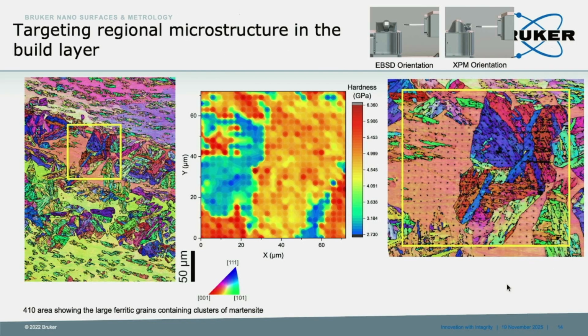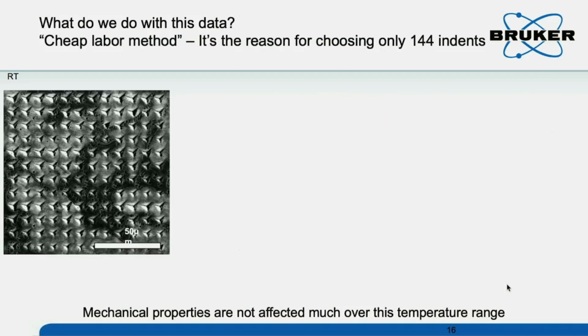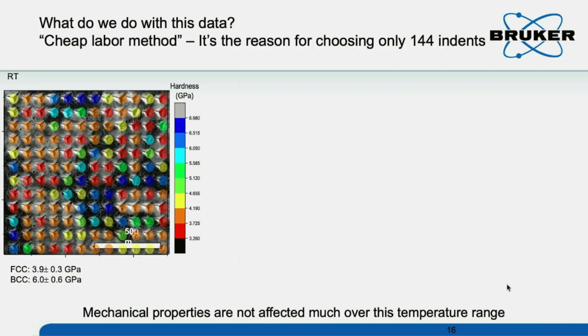And this is also an example of another material with high-speed mapping inside the SEM. You can see this is an EBSD mapping. This is another case, which we call a high entropy alloy. High entropy alloys have different phases. If you look at this, these are FCC and BCC phases, at around 4 gigapascals and 6 gigapascals.